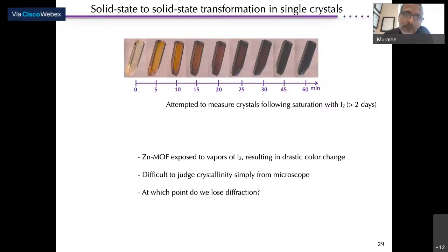So when you expose it to iodine vapors, you can see this is the original MOF, pale yellow. Quickly, within a few minutes, you can see the color change, and within 1 hour, it goes to a dark black crystal. And you can see the edges are still very sharp. So we had a bit of hope that it retains its crystallinity, and we should be able to see, once the crystals are exposed to 1 hour of iodine vapors, and then do the single crystal X-ray diffraction.